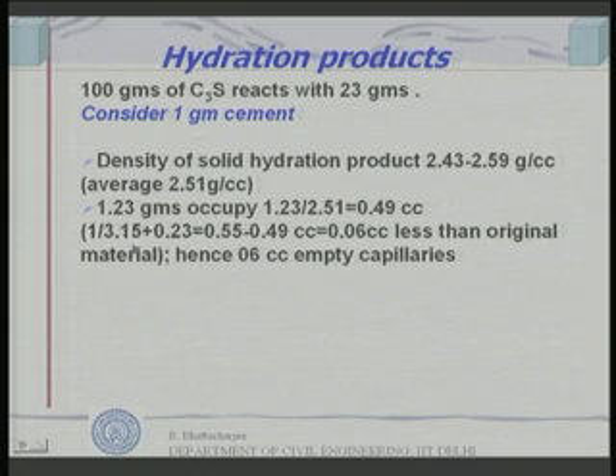1 divided by 3.15 is the volume occupied by the cement originally, plus the volume occupied by water, because the density is 1 gram per cc. That will result in 0.55 cc, and this is 0.49 cc. So this difference, 0.49 cc, is the volume occupied by the solid product of hydration.